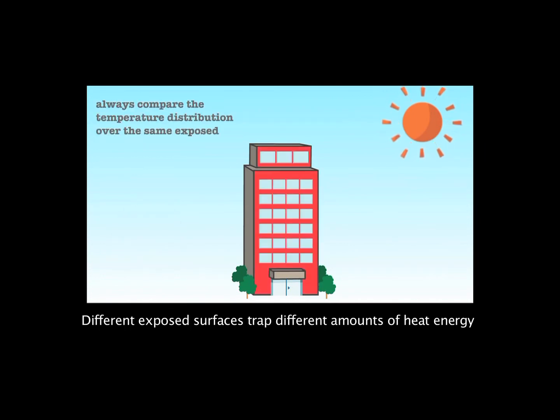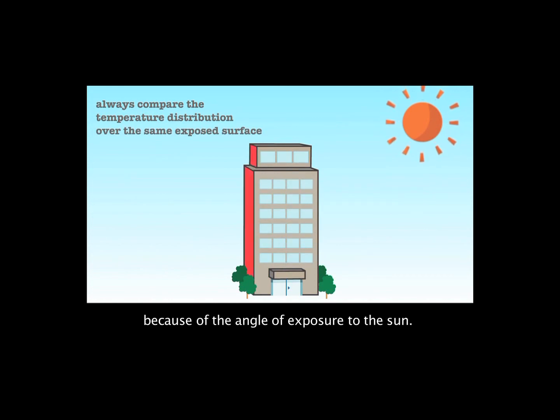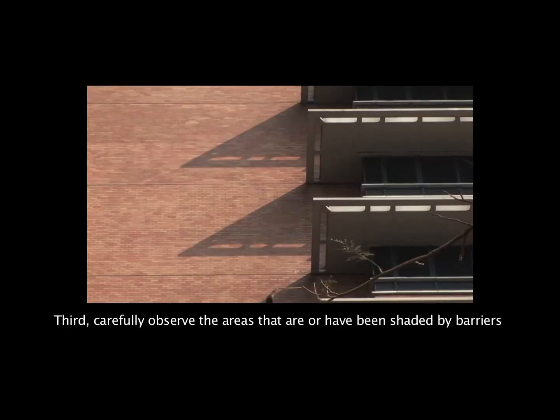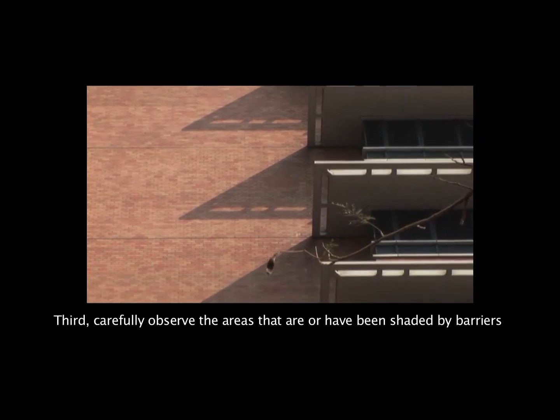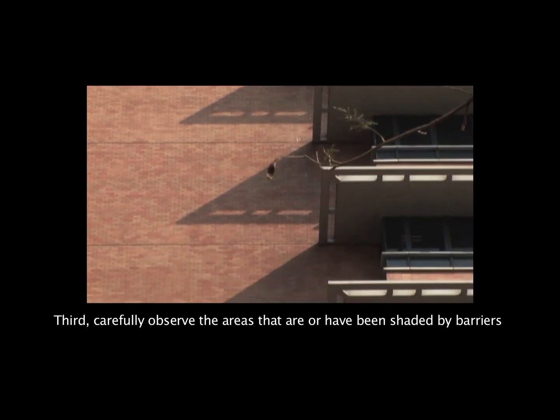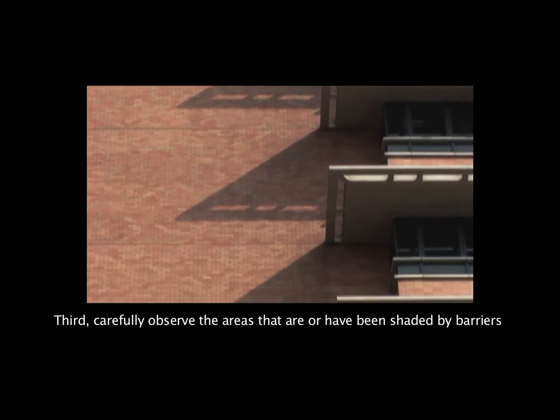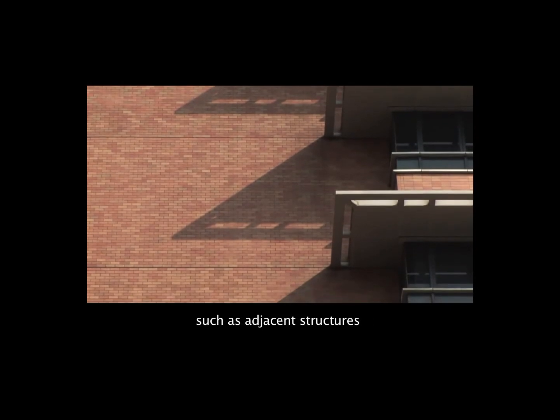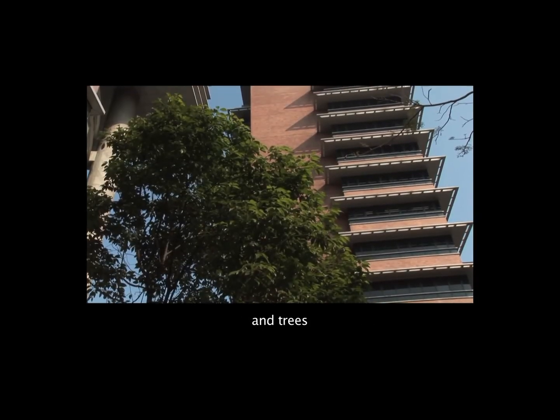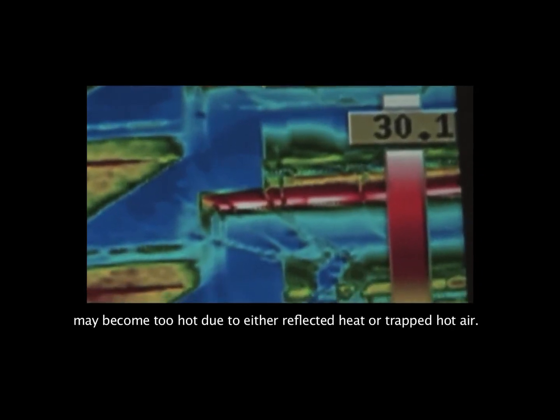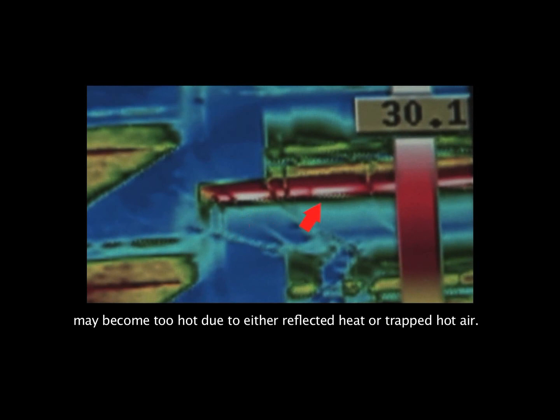Different exposed surfaces trap different amounts of heat energy because of the angle of exposure to the sun. Third, carefully observe the areas that are or have been shaded by barriers, such as adjacent structures and trees. Areas adjacent to barriers may become too hot due to either reflected heat or trapped hot air.